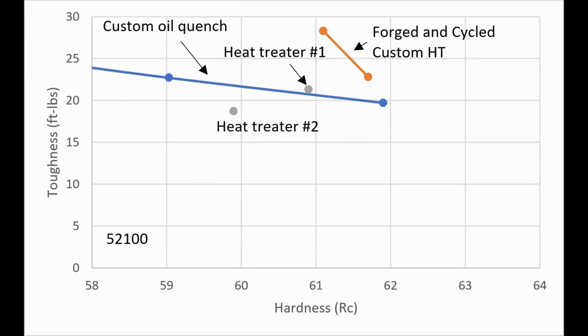So I have a chart here where I have the same 52100 results I showed earlier, but now I overlaid that with some 52100 that my father Devin Thomas forged and thermocycled. In this case, the toughness was higher for a given hardness in the steel that was thermocycled. And this is because of the change in the carbide structure. This is published in an old article on my website, which I will link in the description.